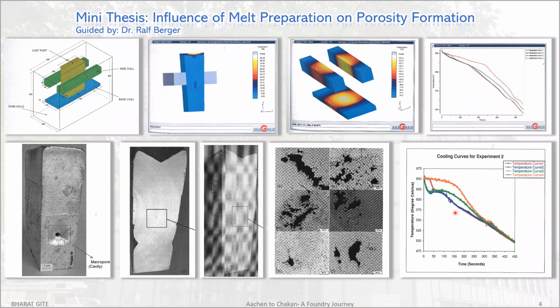High hydrogen gas content leads to higher gas porosity, it is clear. The number of pores in casting increases with a high amount of oxides. Of course, the porosity formation will automatically lead to the precipitation of aluminum oxides, and the brittle phase will form. Gas porosity is desirable sometimes to compensate the volume shrinkage. As all of us know, locally in some areas we want to have more gas porosity to compensate the shrinkage porosity. High temperature leads to high hydrogen content in the melt, especially after 660 degrees Celsius. Lastly, the hydrogen gas can be reduced with the argon atmosphere.